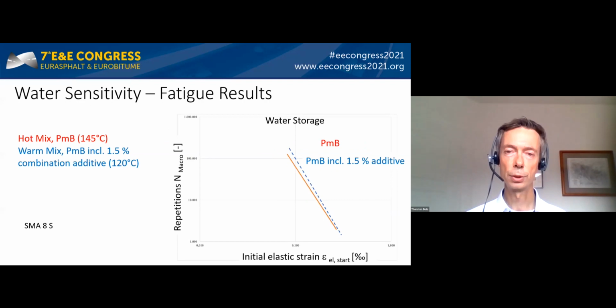Jumping to the water stored samples, we see quite similar results. Equal fatigue functions with slight benefits for the Warmix. This result shows that it is possible to produce Warmix asphalt without compromising the water sensitivity.